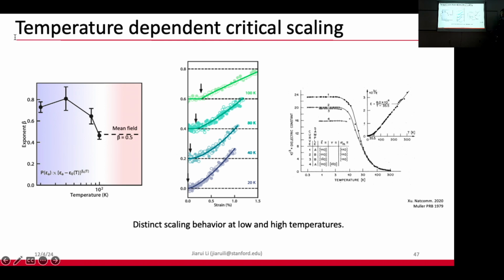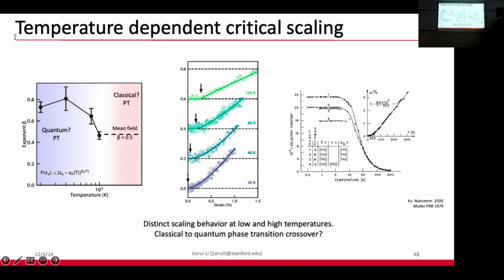So what we believe is that it goes from a classical phase transition at high temperature, where this order parameter-strain critical exponent is around 0.5, and when we cool down, it deviates from the classical phase transition regime, since the quantum fluctuation gets stronger and stronger as we cool down, and therefore this system is deviating from a classical model and entering a quantum phase transition regime. Therefore, you see an enhancement of the critical exponents.